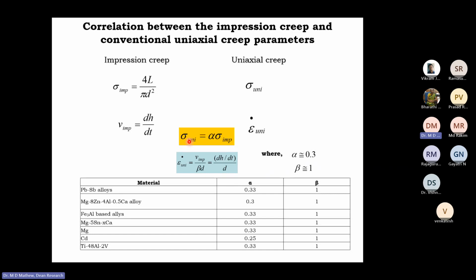The mean pressure can be related to the uniaxial stress sigma using a relationship: sigma uniaxial is equal to a constant alpha times the impression mean stress, sigma IMP. We have calculated sigma IMP as 4L by pi d squared, multiplied by the constant alpha, and then you get the equivalent uniaxial stress. It turns out that alpha is around 0.3 for a large number of materials. You will see here alloys and metals, quite a bit of them, and the value of alpha is all about 0.3. So it's a constant. You ask me why it is a constant, I have no idea, but that is the empirical evidence. So you have got the uniaxial stress.